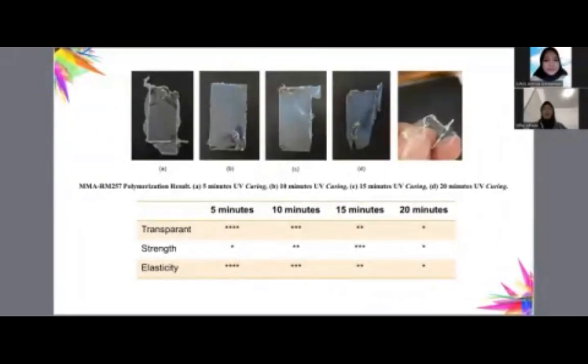This picture is the result of polymerization of MMA and RM257 with variation in UV curing time. It can be seen that the sample with a UV curing time of 5 minutes has a more transparent color than other samples, but the texture is very susceptible to tearing and is difficult to remove from the substrate. The texture gets stronger along with the length of the UV curing process. The sample with a UV curing time of 20 minutes has a strong texture, breaks easily, and is less elastic. This is because the curing time is too long, causing the sample to atrophy.